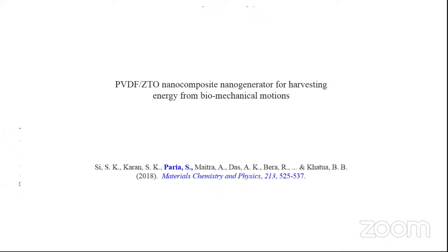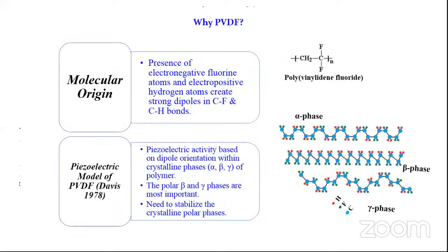In our third system, we have used a ferroelectric polymer as well as a ferroelectric oxide. Why have we chosen PVDF? If you see the backbone of PVDF, you will see CH2 and CF2 groups. Depending on their arrangement on the backbone, we have different phases: alpha phase, beta phase, and gamma phase. The alpha phase is nonpolar, the beta phase is polar, and the gamma phase is slightly polar. The piezoelectric output performance of a PNG depends on the amount of beta phase.